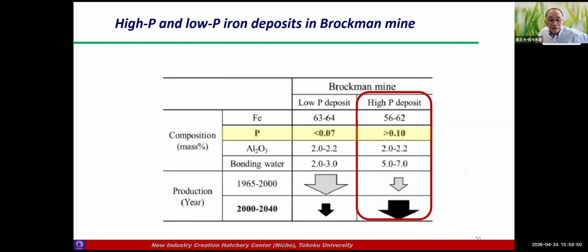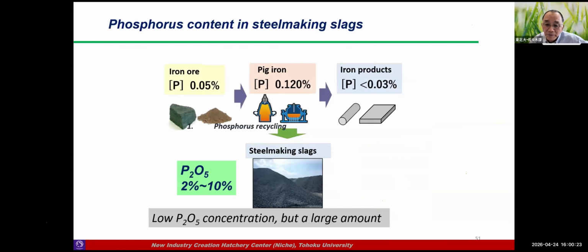If you look at iron ore with phosphorus impurities, previously, up to around 2000 years, the phosphorus content was less than 0.07. But after 2000, the amount of phosphorus gradually increased, and now it has maybe reached 1.2 or 3. So the amount has been increasing a lot. In the future, we may get much more phosphorus in steelmaking slag.